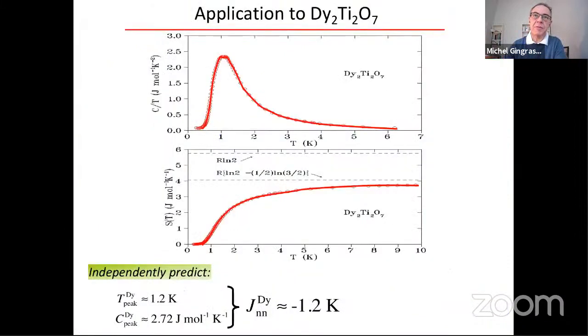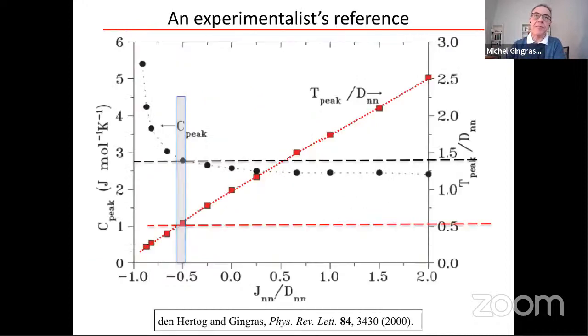So we can then try to fit the experiment and try to understand if this makes sense. Are the experiments in these compounds compatible with these dipolar interactions? Again, the dipolar coupling constant is known, and so the only free parameter is J. We can go back to the experiment and look at the specific heat. What one finds is that there's one key feature in the specific heat: the location of the peak and the height of the peak. So that gives us two quantities one can fit to extract one free parameter, which is J. So it's a very constrained model. And this is what it looks like. We can fit, as a function of J over D, the location of the peak in the specific heat. This is this red curve here, or pretty much red straight line.